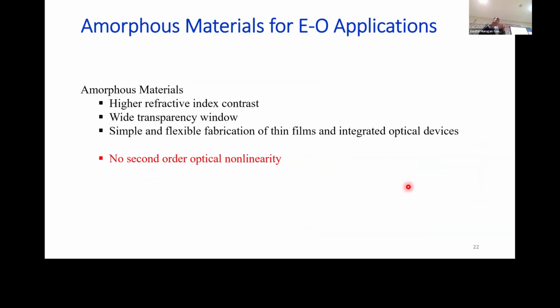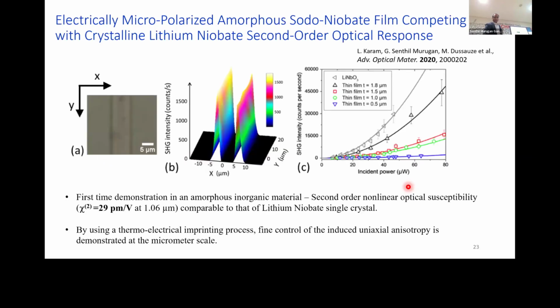nonlinearity. Because amorphous materials or glasses don't have Chi2, as you may know, because of the isotropic nature, but we introduced the Chi2 by breaking the symmetry, and we achieved Chi2 nonlinearity up to about 29 picometer per volt, which is very close to what you can achieve in one of the directions of lithium niobate, which is 35 picometer per volt.